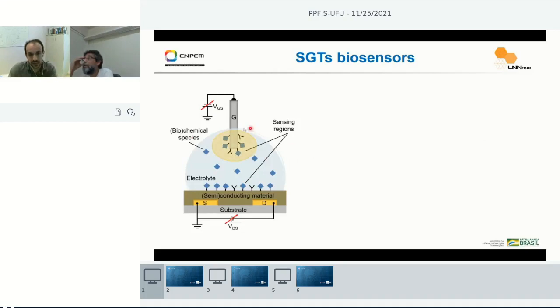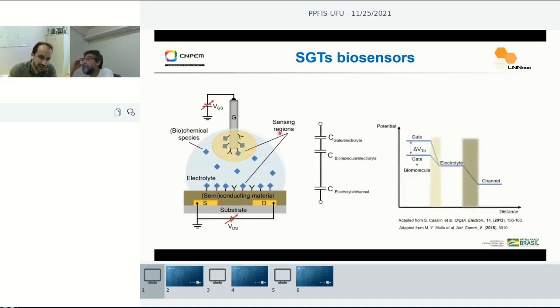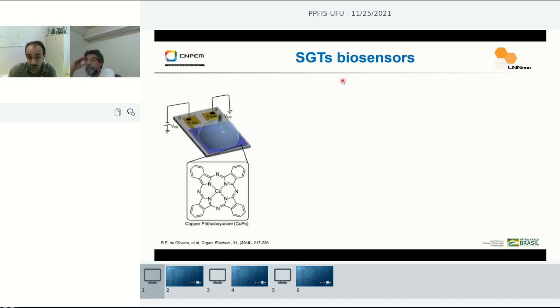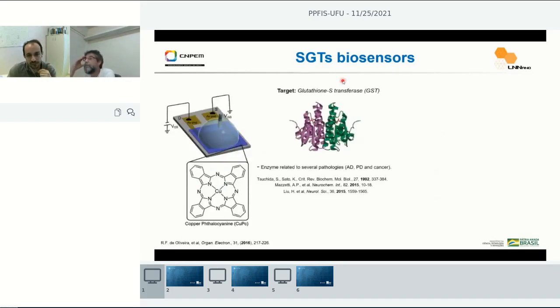in solution. This means that, for example, if I functionalize the gate electrode, I will promote some change at the interface capacitance here due to the presence of a bioreceptor or biomolecule at this interface. Physically speaking, what happens is that we change the effective gate potential that controls the channel. And that's what we did for a given biomolecule